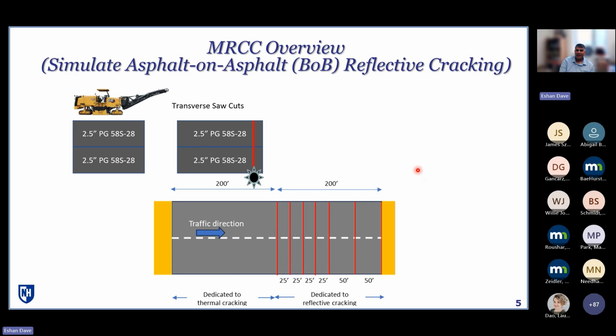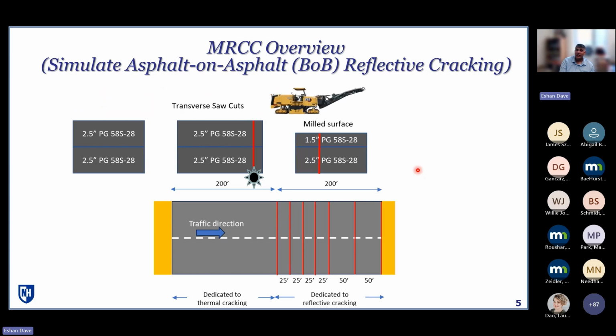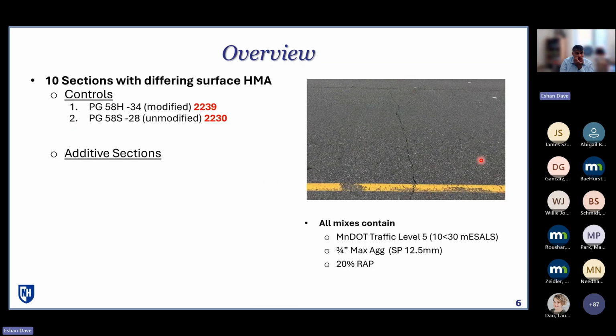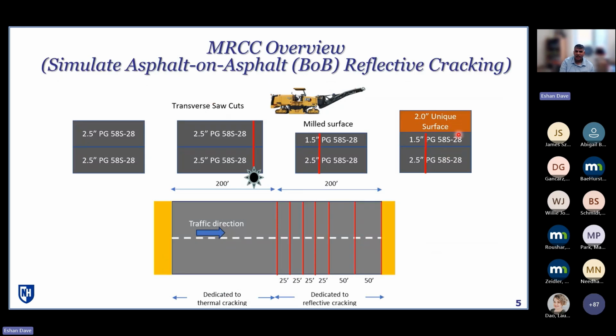So once the saw cuts were done, the next step was to go with a milling machine, and that removed the top inch of the top 2.5 inch lift, leaving behind 1.5 inches of that initial asphalt with the saw cut in it for half of the section. And then a 2-inch unique surface was placed. It's called a unique surface because that is the only variable in each cell. So between those cells, the rest of the structure is identical. They all have the same type of layout as you see on the bottom. They all have the bottom 4 inches and everything below identical to each other. So what are these unique surfaces? There's 10 cells, 10 different mixes.